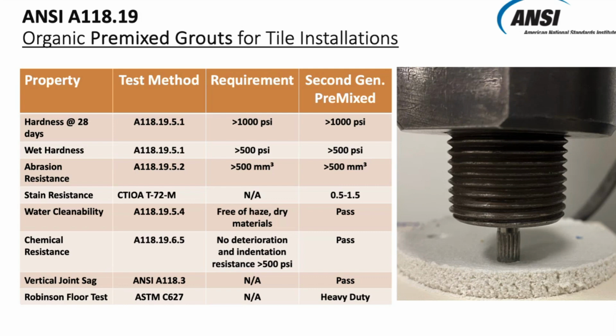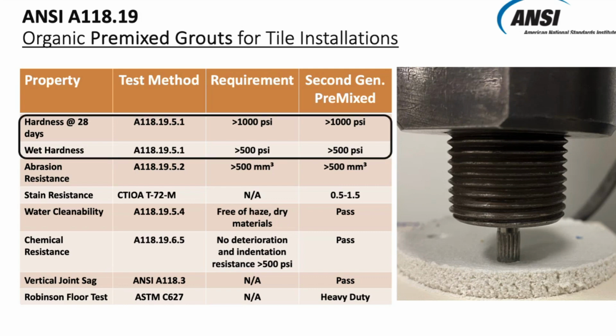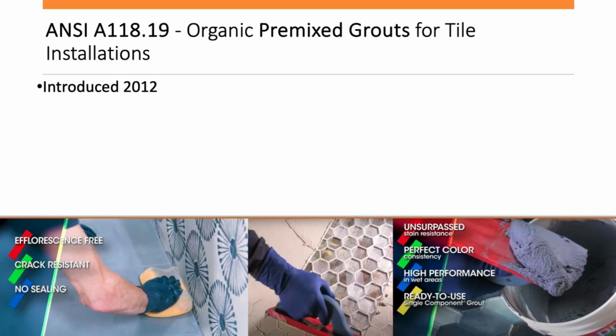Now what you're getting here, you get a hardness after the 28 days. So we still rate it to that 28-day cycle because we do compare it with our epoxies and our cement-based grouts. We keep everything within that 28 days to keep it consistent on our testing. The requirement was to get over 1,000 PSI. We got that with the second generation premix because by now we are on the second generation. We'll talk about that in a little bit. And then everything else, it passed. We'll talk about some of these tests.